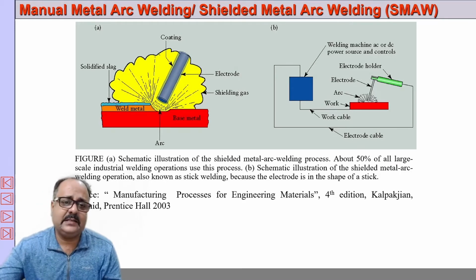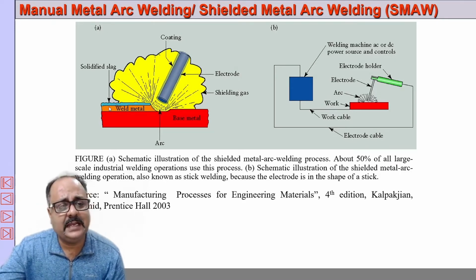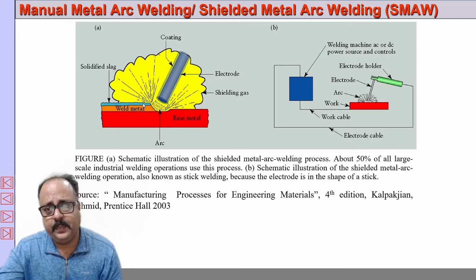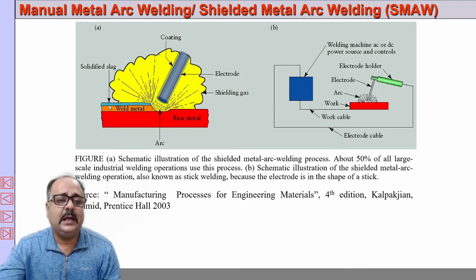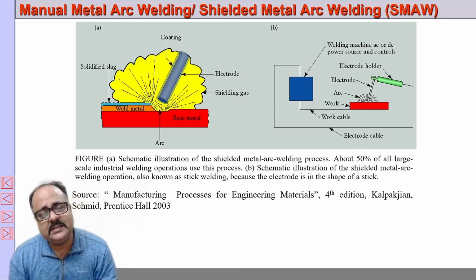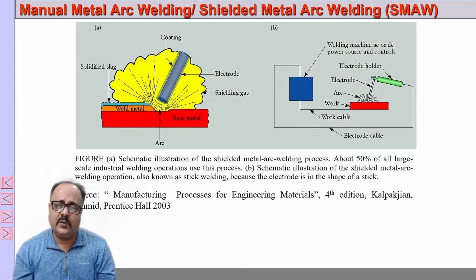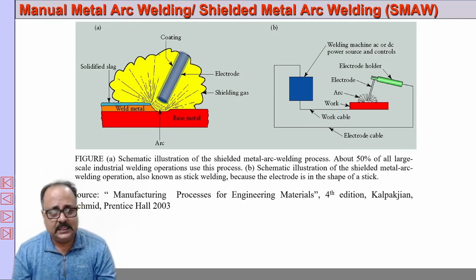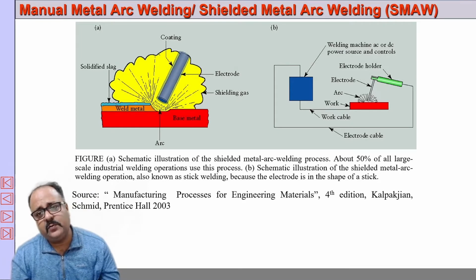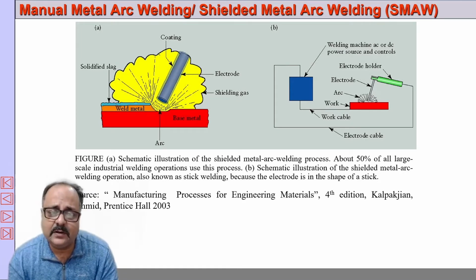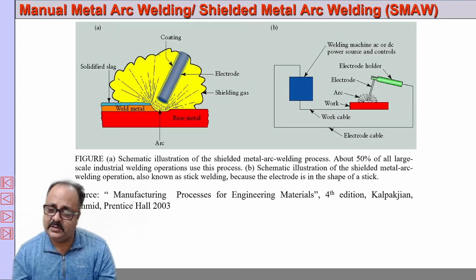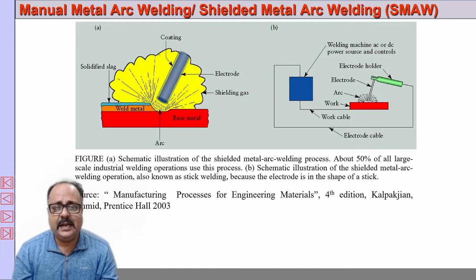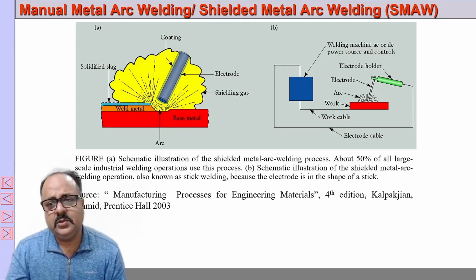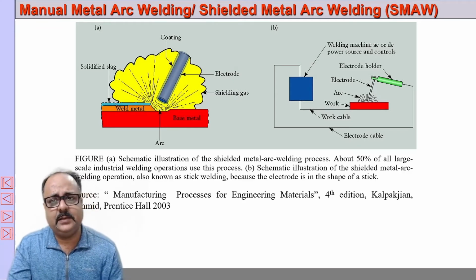And once the metal solidifies along with the solidified slag, it will be removed by a chipping hammer. So this is one of the reasons why it is difficult to automate, because this slag has to be removed before we go for the second pass. After each pass, the slag has to be removed meticulously, and if you don't remove it meticulously, in the next pass slag will be entrapped. So that is a defect called slag entrapment. So this slag removal is also a problem in this type of welding process.